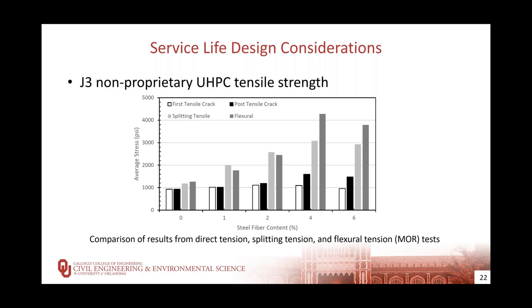UHPC tension strength is an important consideration for UHPC Link Slab design, and this slide shows a comparison of tension strength results from direct tension, splitting tension, and flexural tension, or MOR, testing relative to fiber content. In all testing, we examined 0% steel fibers to provide a baseline for the matrix, even though this would not technically qualify as a UHPC since it has no post-cracking behavior.